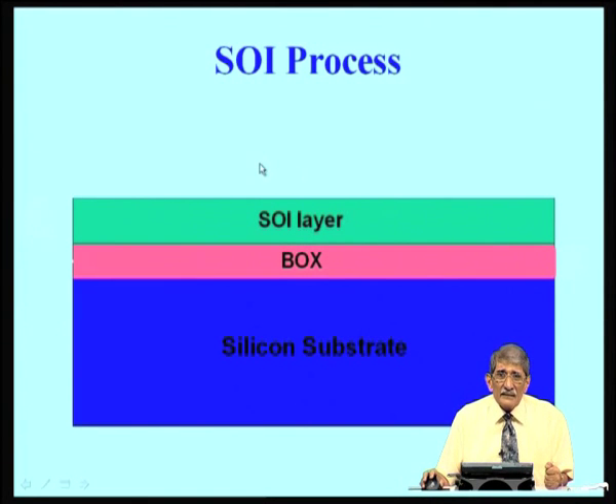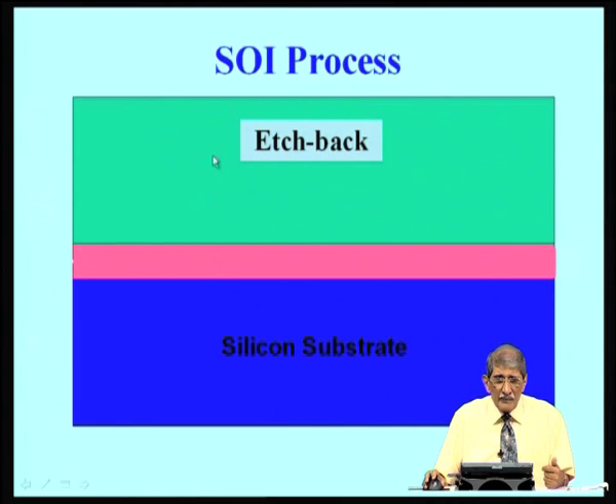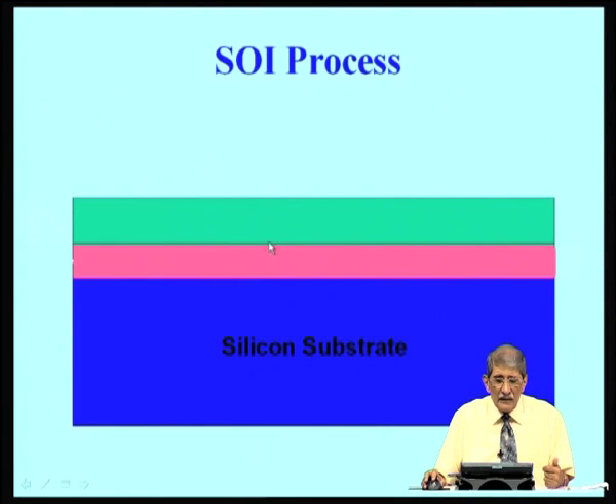Why do you reduce it to the required thickness? You need a thin layer for integrated circuits. Also, I can use this for realizing a membrane for making a pressure sensor, and the membrane thickness will be decided by how much the SOI layer thickness is. So, if I want a 10 micron thick membrane, I will have to reduce this layer to 10 microns. Originally that must have been 200 micron, I will etch it down, reduce it to 10 micron. So, you can use this layer to realize the pressure sensor and also electronics.